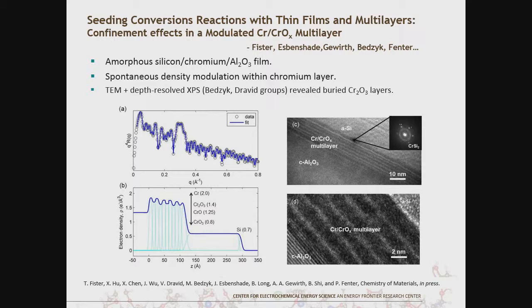This is X-ray reflectivity data. There's this peak here, a Bragg peak corresponding to these layers that form. If we solve the structure, the blue line is a fit, and this is what the density profile looks like. This is the density, the multilayer structure. It was actually created with a silicon film on top, which of course is going to lithiate as well, but our focus is actually on the chromium oxide material.